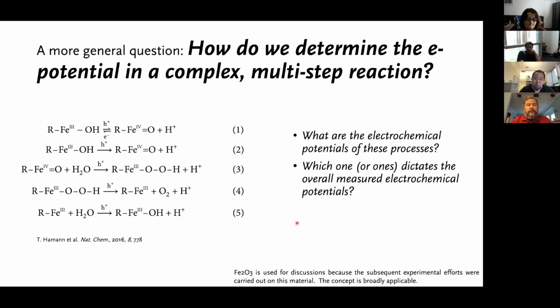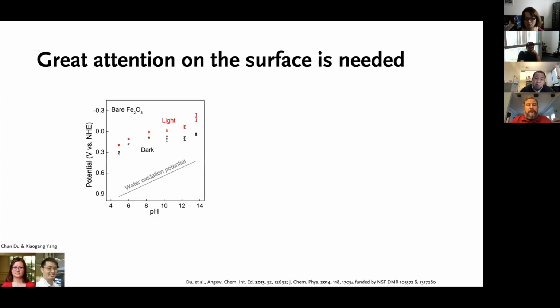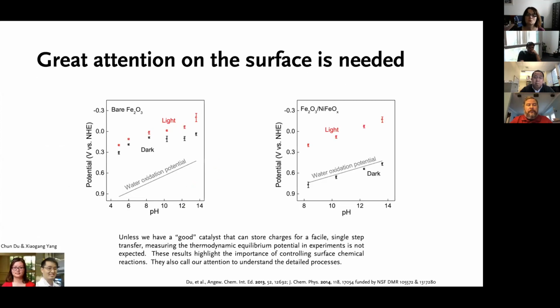So if you come back to this here, you really need to ask the question, are we really measuring the overall electrochemical potential? Are we measuring one of the slow steps in the process? So that's a question you should be asking. The bottom line, really the punchline here, is that once they coat the surface with a known good catalyst, amorphous nickel iron oxyhydroxide, they were able to reliably measure the potential where the water oxidation potential is expected.